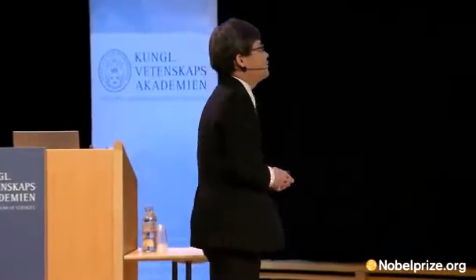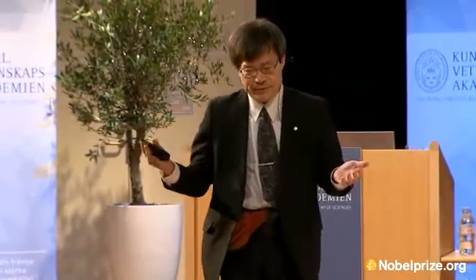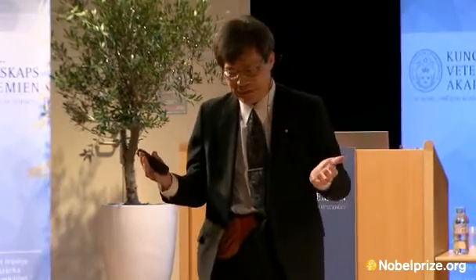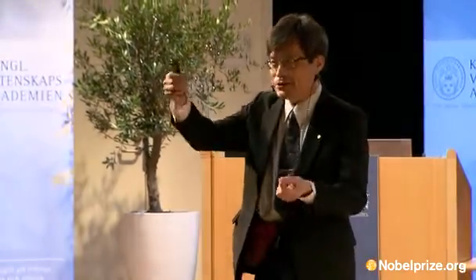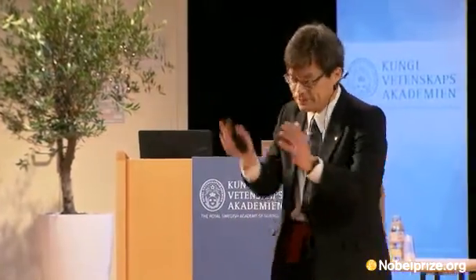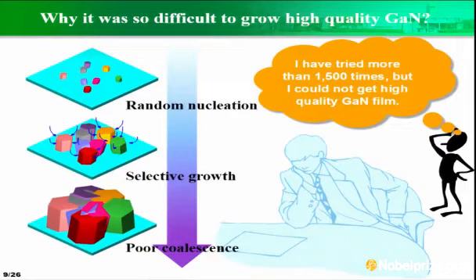I tried more than 1,500 times by changing the growth conditions such as growth temperature, growth flow rate, liner tube configuration, and the susceptor shape, and so on and so on. But unsuccessful. I could not get high-quality gallium nitride film. For me, the large lattice mismatch was too great to overcome. So almost 2 years passed without success.